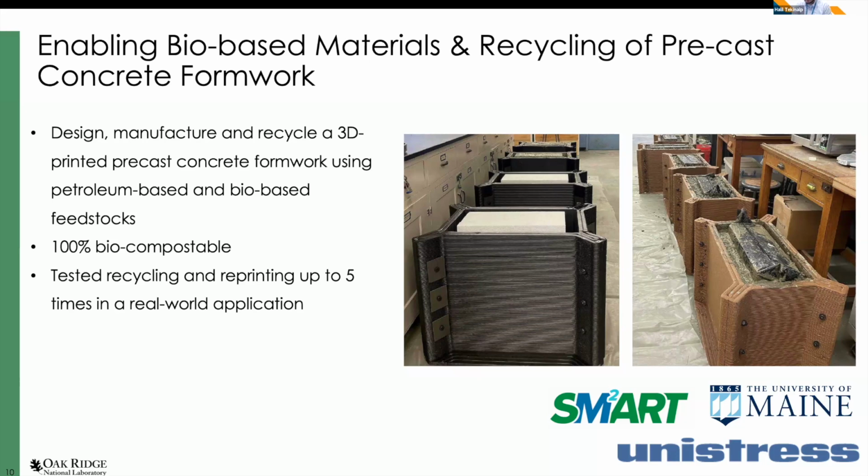We pour parts out of them, and then we clean them, and then using the capabilities you saw in the previous slides, we shred and granulate them and then repelletize them into uniform pellets, and we print them again. We are repeating this cycle 5 times, and we are already in the 4th cycle. It's been working fine, and we have no problem. And then we're investigating all the changes.